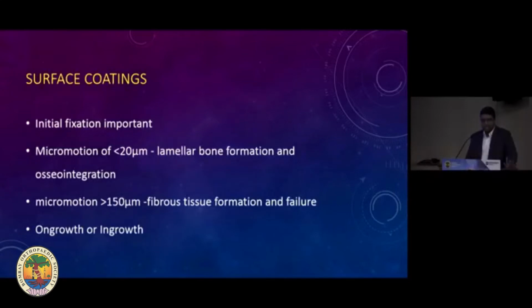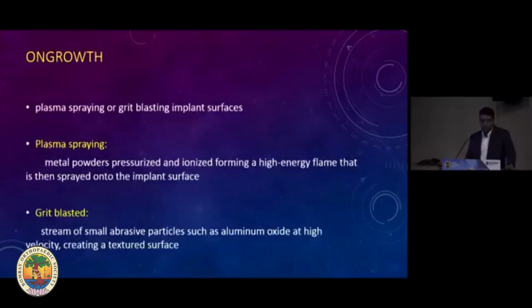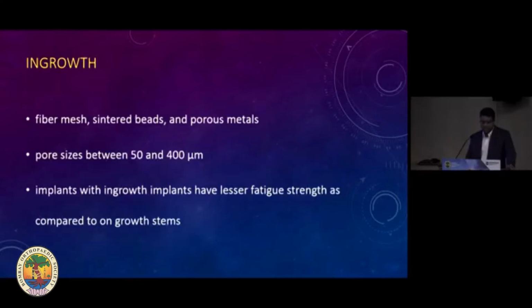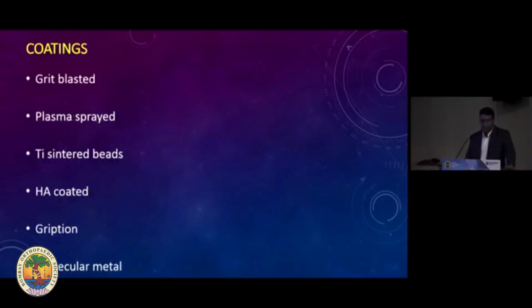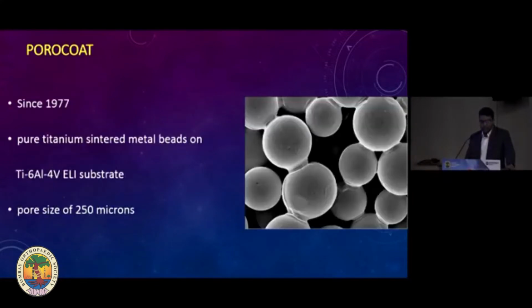Surface coatings, whatever we may use, the initial fixation of the implant is primarily important because a micromotion of less than 20 microns can lead to good ingrowth or on-growth. For on-growth, the stems are usually plasma sprayed with metal powders, or they are grit blasted, blasted with hard abrasive particles of aluminum oxide, which leads to a roughened texture. For ingrowth, there are fiber mesh, sintered beads, or porous metals with a pore size of 50 to 400 microns, which lead to better ingrowth. These are the coatings: grit blasted, plasma sprayed titanium, sintered beads, HA coating, Gription, trabecular metal.